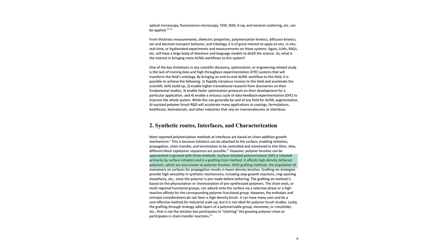This method, often called surface-initiated polymerization, or SIP, is highly effective for achieving the high grafting densities needed for true polymer brushes. The second method is grafting onto. In this approach, fully formed polymers are synthesized first, with a reactive functional group at one end. These pre-made polymers are then brought into contact with a surface they can bond to. While this method is versatile, the chains that have already attached to the surface create a steric barrier, making it difficult for new chains to approach and attach. This entropic and enthalpic penalty means that grafting onto typically results in lower grafting densities compared to grafting from.